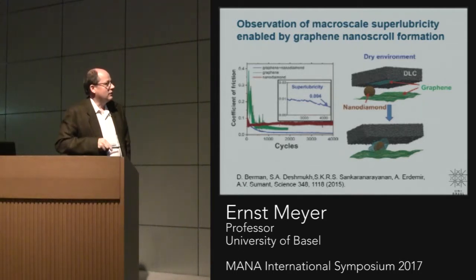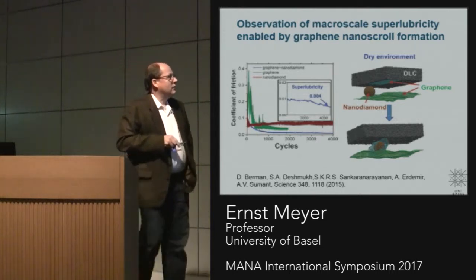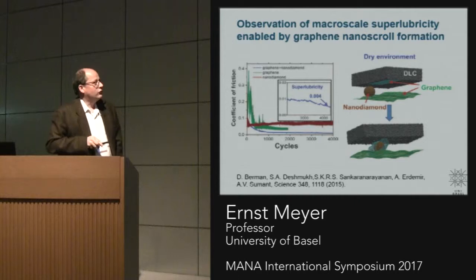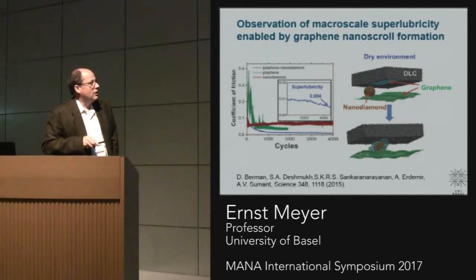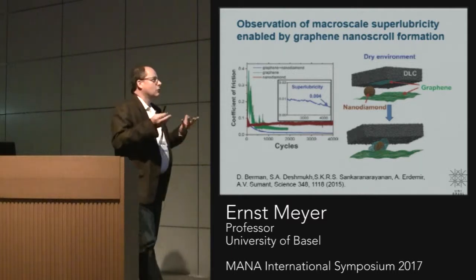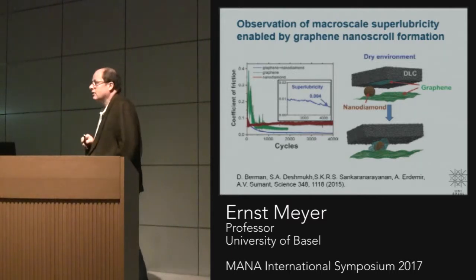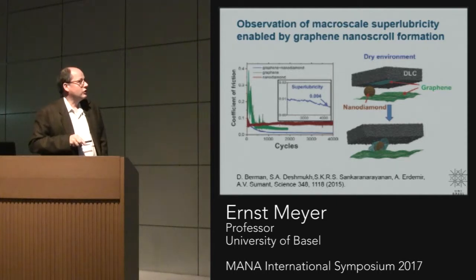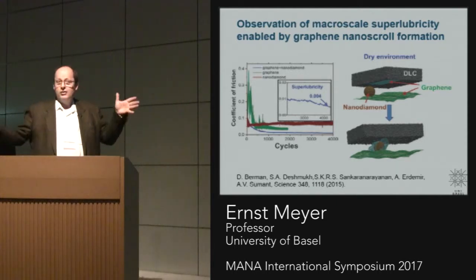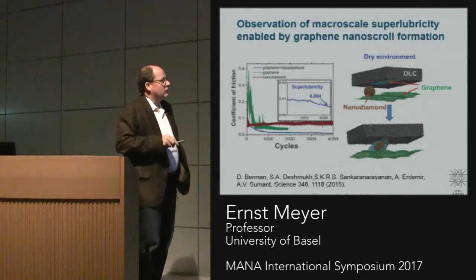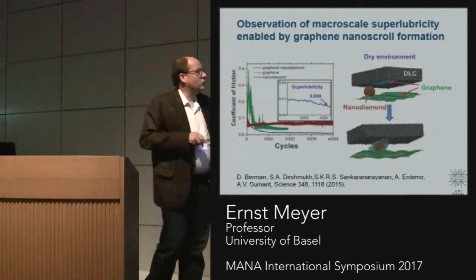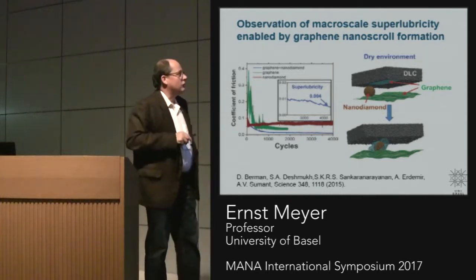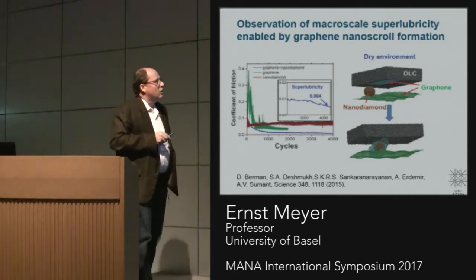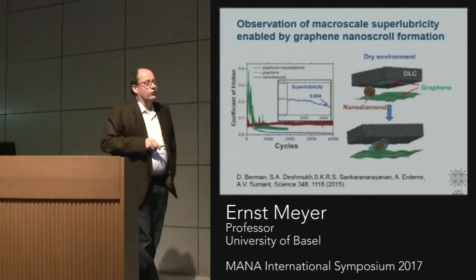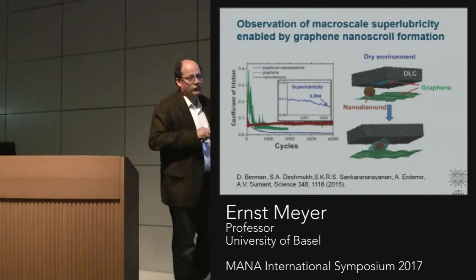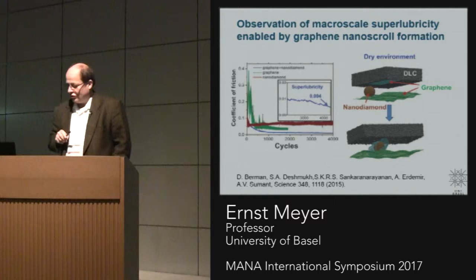And actually this is an example from the group of Ali Erdemir from Argonne Lab, and they have used DLC, so diamond-like carbon, with diamond and graphene. And if you do the experiment in a dry environment, you actually can see really very low friction, and actually for many cycles. Superlubricity in that sense is also defined by the friction coefficient, so just the ratio of the friction force divided by the normal load, and so this is 0.004. If it's below 0.01, one usually calls it superlubricity in this more technological application.